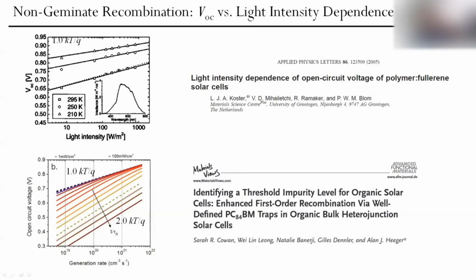So it has been shown by a number of researchers that the slope of open circuit voltage in semi-logarithmic scale against generation rate or light intensity, because they are linearly proportional, the higher the light intensity, the higher the generation rate of excitons, can change from unity in terms of kT divided by q, like Boltzmann constant multiplied by absolute temperature divided by charge of electron, to 2.0 kT. So this works in two cases. First of all, when we have 1 kT over q, the bimolecular recombination mechanism dominates, and when we have 2 kT divided by q, then we can claim that the trap-assisted recombination mechanism dominates.